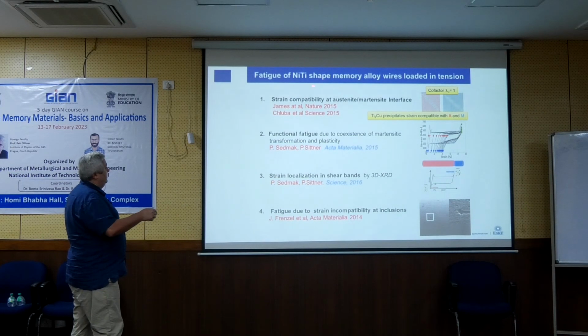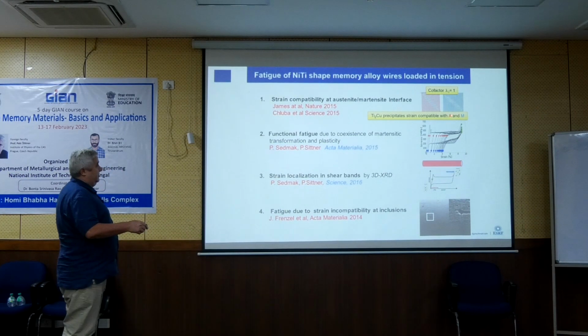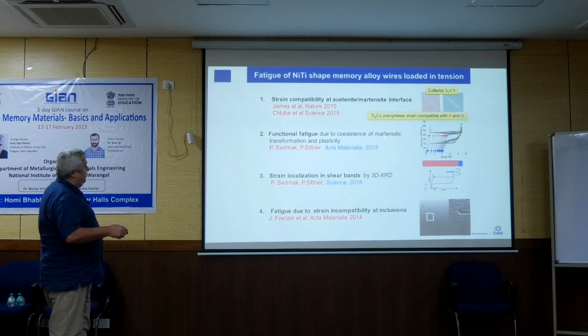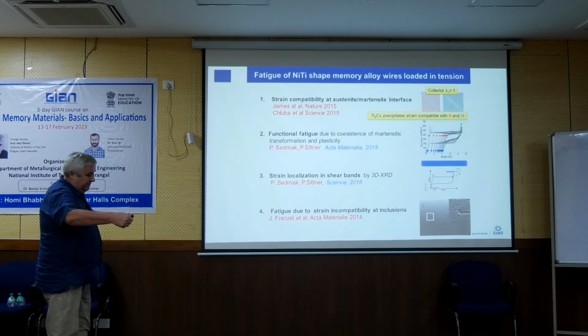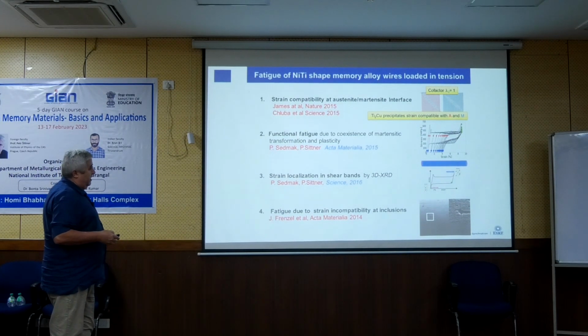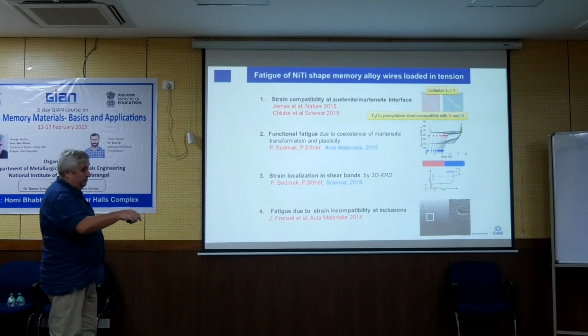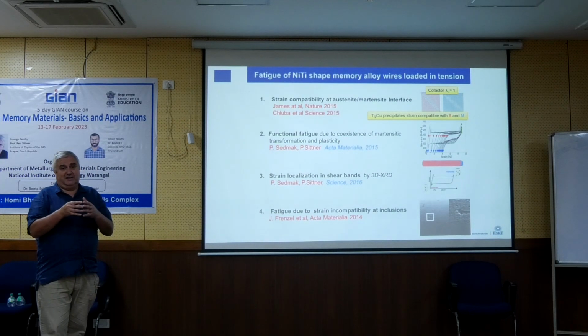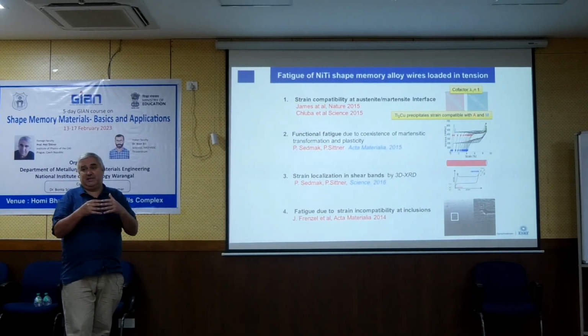So first of all, it is this strain compatibility, the austenite-martensite interface. This is still relevant. There should be problems with this localized deformation, because when we do the test in wire tension, we will have it. And of course, when the deformation is localized in such a band, this localization is really a problem for fatigue.